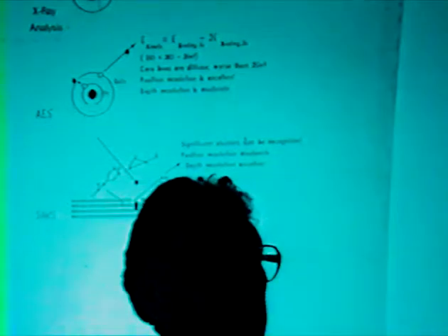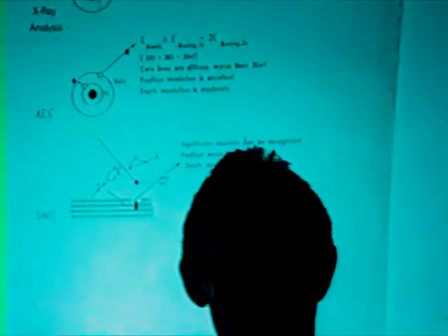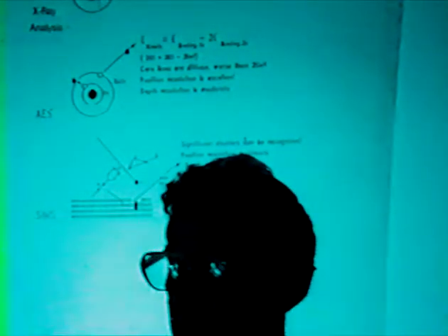In the old days, that is up to about 3 years ago, everyone complained that this was a very destructive technique and you'd hardly blinked before your surface had gone. But nowadays, with a time of flight SIMS instrument, you can get very good spectra. In fact, you can get complete maps using an ion dose which is only about 1/10,000th of a monolayer. So you do very little damage to the surface.